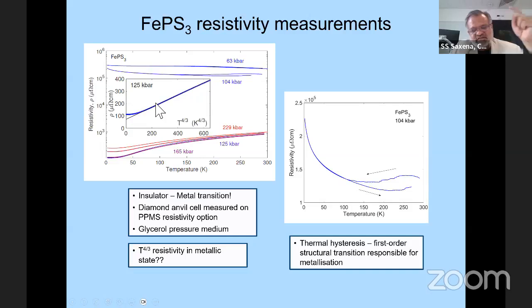And unlike intermetallics or other things, here it persists to pretty high temperatures compared to those materials. And also we find that there's some other interesting behavior at low temperatures. At the very low temperature, we have an upturn, which we're trying to understand. This could potentially be something like a Kondo effect, which is being nucleated because of magnetic localization that might be happening in these materials. But we have no proof of that, it's just speculation. But the metal to insulator transition, or Mott transition, in the material is quite interesting, and the fact that it comes with this new correlated behavior, or breakdown of the Fermi liquid state, is also interesting.